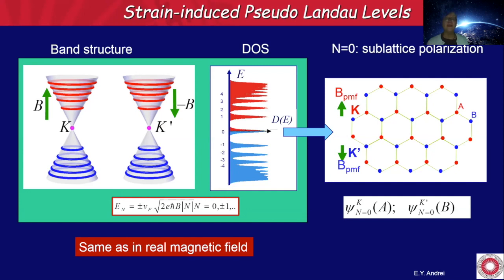Now, if you have a real magnetic field, this would be an effect that is completely undetectable. But with pseudomagnetic field, as we will see in a moment, if you can separate positive and negative pseudomagnetic field, you can actually see, in one case, only the red sublattice being populated, and in the other case, only the blue sublattice populated. And that's what will tell us, when we're looking with the scanning tunneling microscope, the wave function will tell us whether or not we have a pseudomagnetic field.